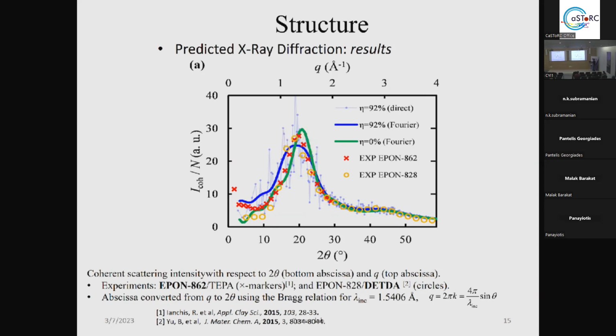With the red and yellow, we can see the experimental values with scattering points. Here again, we see the problem that I told you before, that it is not exactly the same epoxy, but we weren't able to find exactly the same epoxy, with the same hardener, and an experimental XRD pattern. We see here, due to the size effects, some disagreement at that point of the plot.